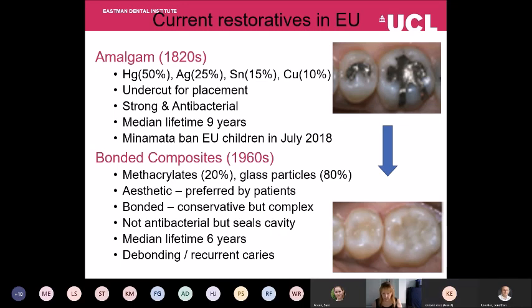The issues are that with a composite, median lifetime is only around 6 years compared with about 9 for the amalgam restoration. And the failure is usually because of debonding and recurrent caries at the tooth restoration interface.